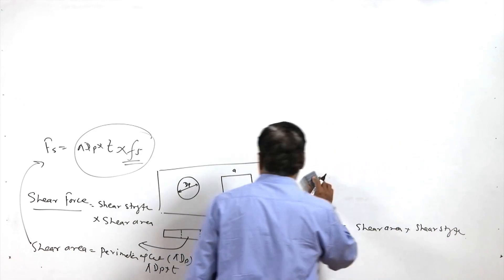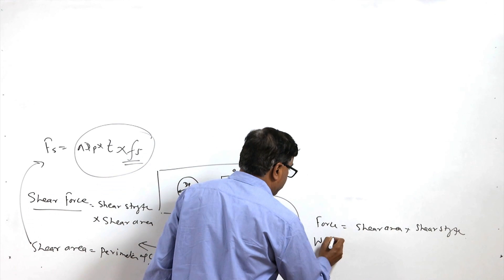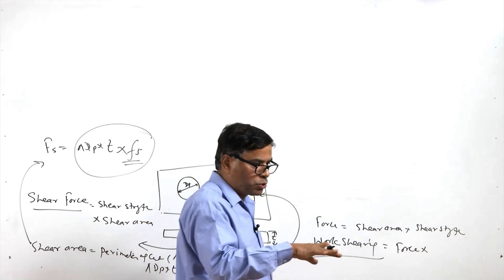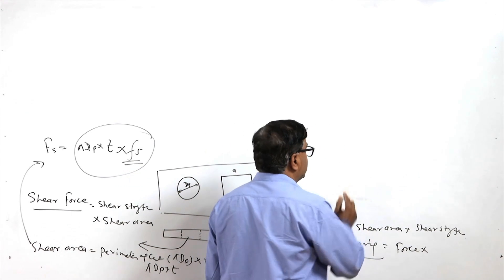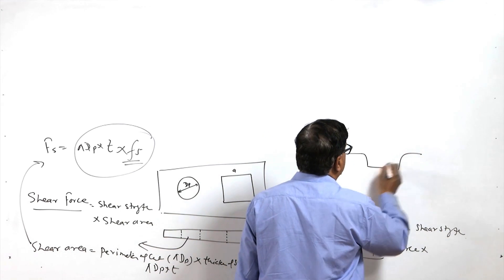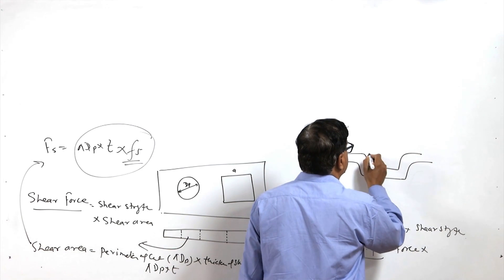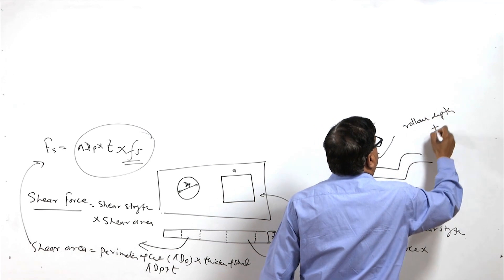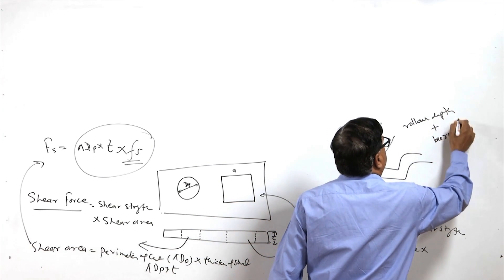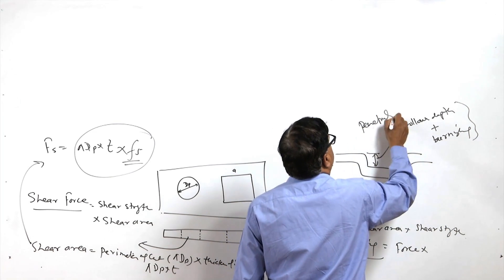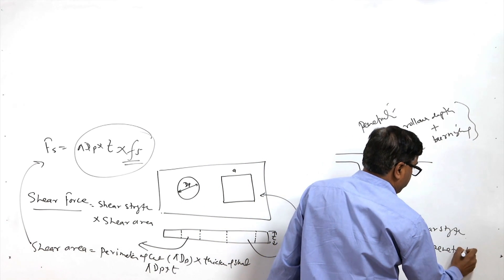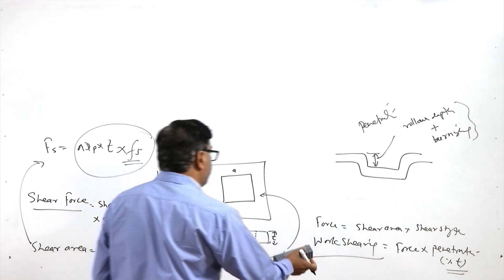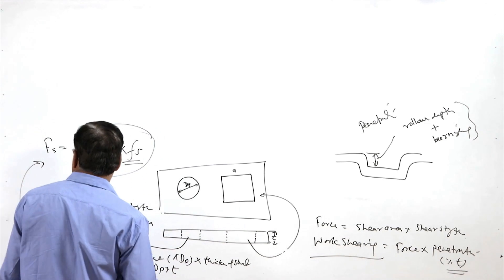If we have the shear force, we can determine the work to be done for shearing. Work for shearing equals force multiplied by the distance through which the force is applied, and that distance becomes equal to the depth of penetration. The depth of penetration is basically the sum of the roll-over depth (deformation depth) plus the burnishing depth. This sum is used as the penetration depth, expressed as a percentage of the sheet thickness. Shear force multiplied by the penetration gives the work required for shearing.